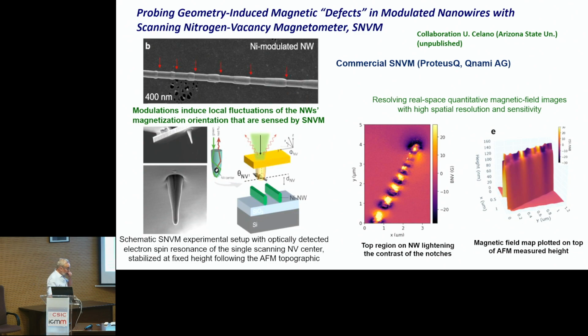This is very recent. I would like to show you this because it's not yet published. It's in collaboration with Umberto Celano, who has been working with this company and now is in Arizona State, with this fashionable technique, the scanning nitrogen vacancy magnetometer. So you see this is the nanowire prepared by Cristina, and with this technique, it's possible to resolve the distribution of these, what he called defects, but these defects are designed in the nanowire. And this is a map of the magnetic field along the length of the nanowire. So this is a very novel technique and probably requires further improvement.